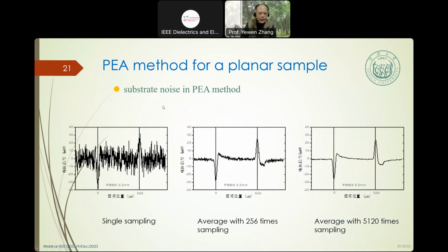Now we can get the PEA method for planar sample. For the noise in the PEA method, one sampling, one measurement has a very low signal-to-noise ratio, but after 256 times average, we can get the signal clear. If we average more measurements, the signal is more clear.